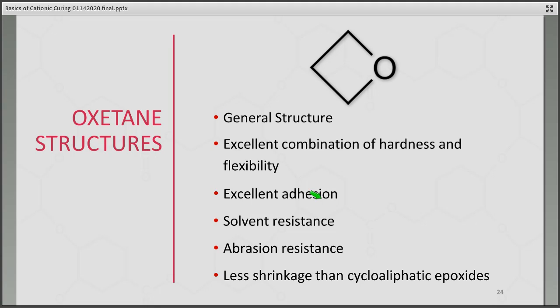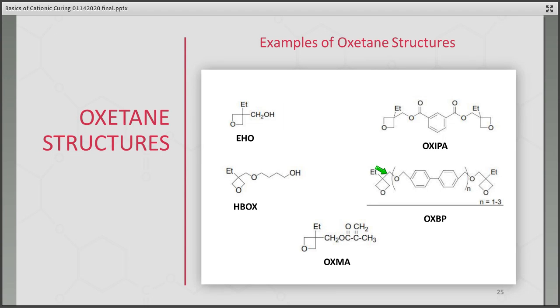There's another cyclic material that is used, and in fact it's being used more and more for a lot of good reasons, and that's using oxetane structures or oxetane materials in your formulation. This is the general structure of an oxetane here, and I'll have some examples of commercial material in the following slide. But oxetanes tend to give a very good combination of both hardness and flexibility, so a good balance there. You get excellent adhesion, solvent resistance, abrasion resistance, and you'll also get less shrinkage than cycloaliphatic epoxides. So they're a very good material. They tend to cost just a little bit more, so they're used in balance with cycloaliphatic epoxides most commonly, or in combination.